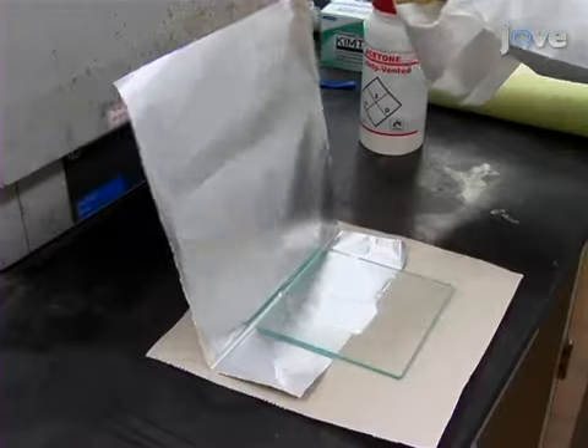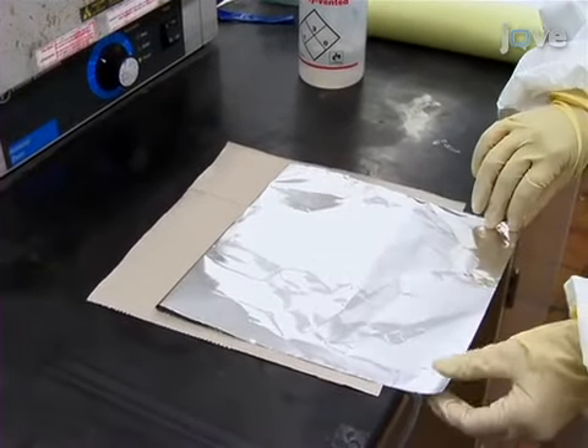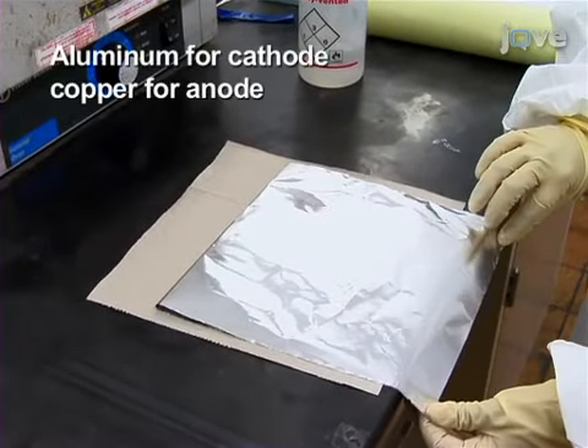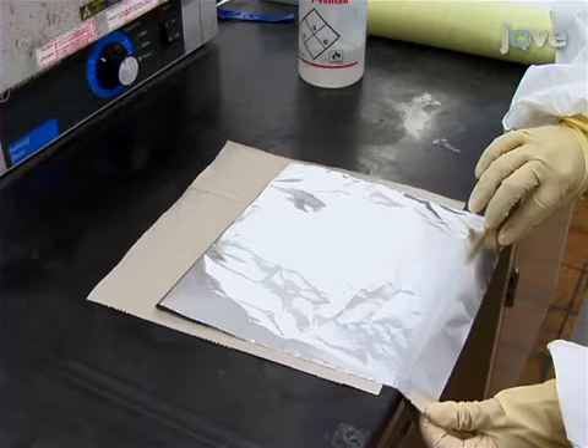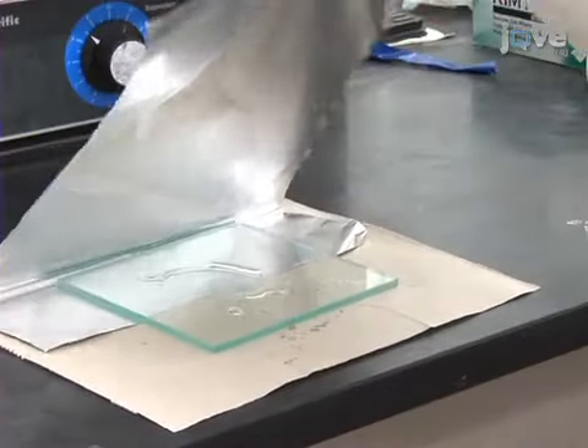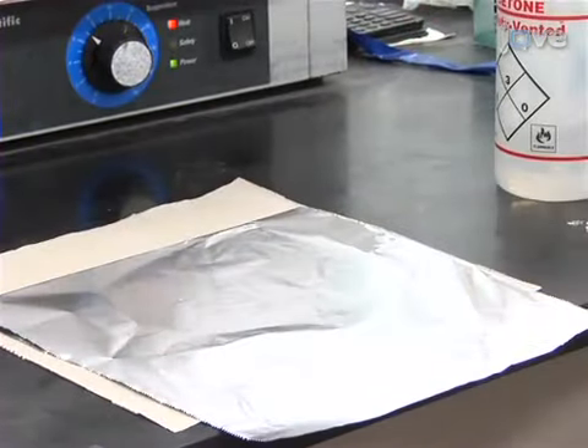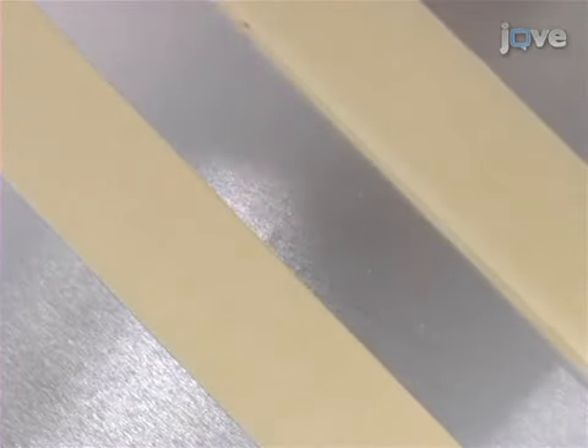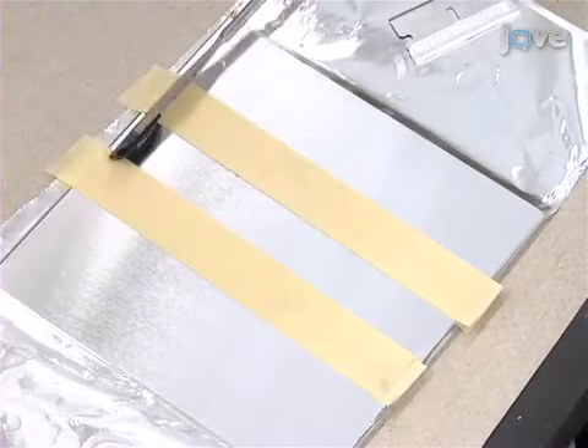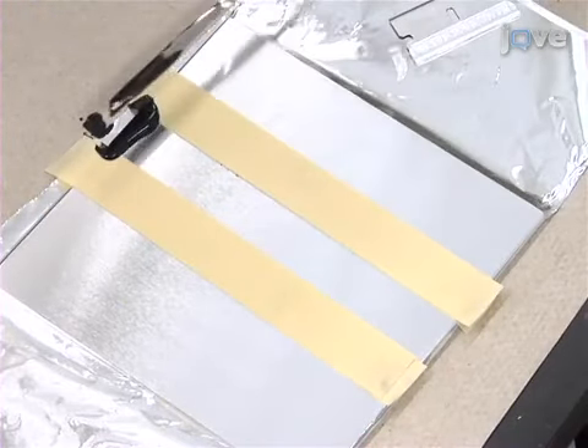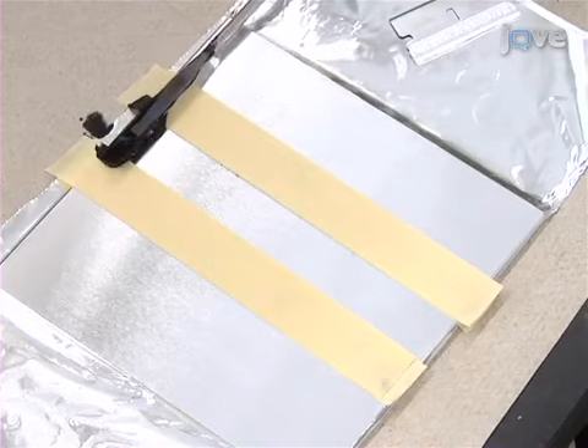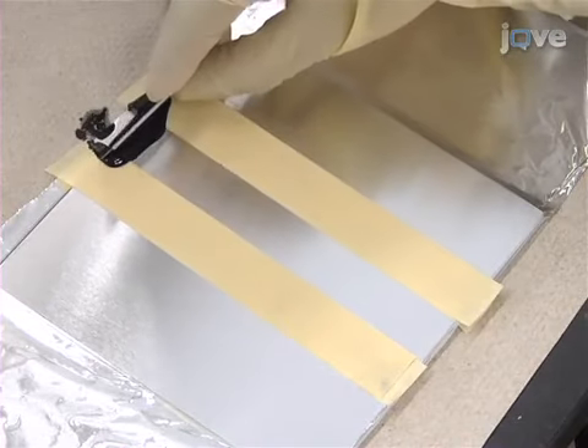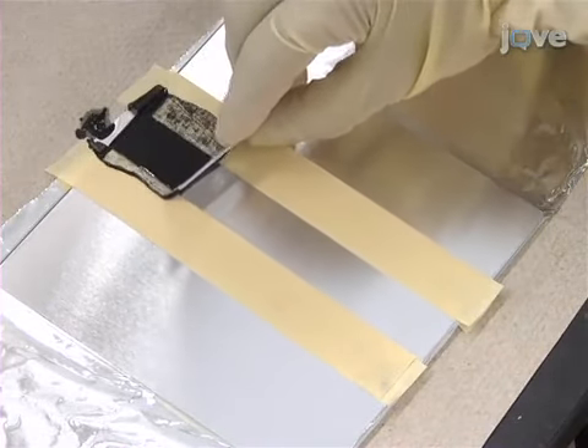Next, spread a metal foil of the current collector onto a glass plate. Aluminum is used as the current collector for the cathode, and copper is used as the current collector for the anode. Use acetone and remove any air bubbles between the foil and the glass plate. Now, position 2 layers of masking tape to define the region to be coated. With a stainless steel spatula, apply the slurry onto the metal foil. Spread the slurry uniformly onto the track using a razor blade.